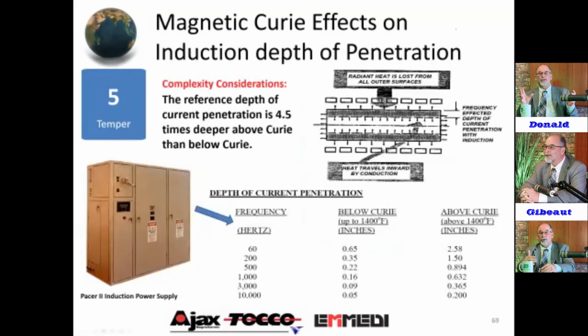Yes. Here we actually show you, if you're looking at 1 kilohertz down here on the lower side, the below Curie heating for that 1 kilohertz is 160 thousandths. You go to the above Curie heating and it's 4.5 times deeper. For the same frequency, you have 632 thousandths. So truly that magnetic Curie point is something that needs to be understood, and definitely a consideration in our simulation software.